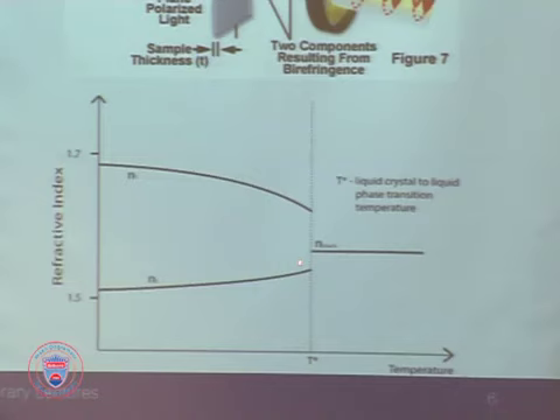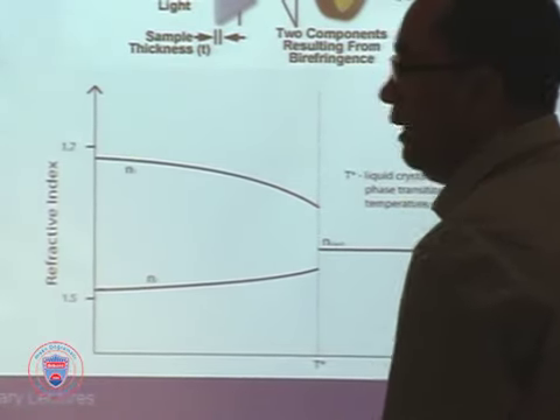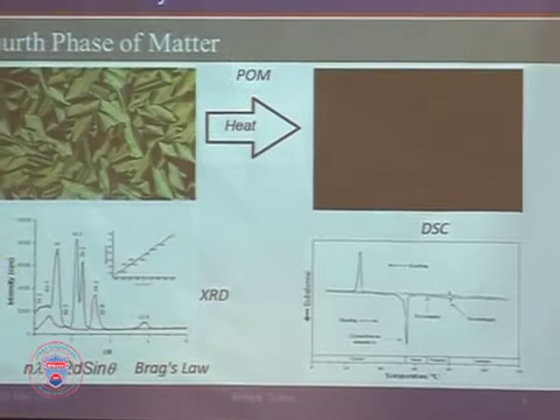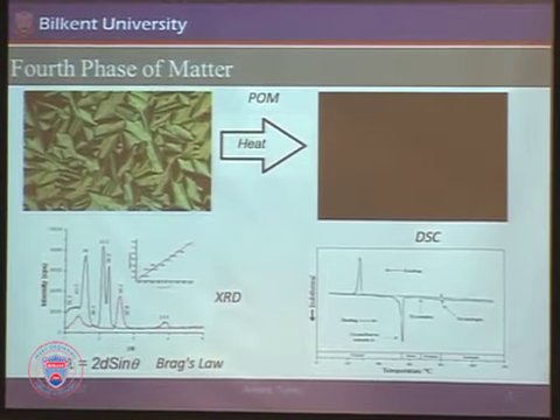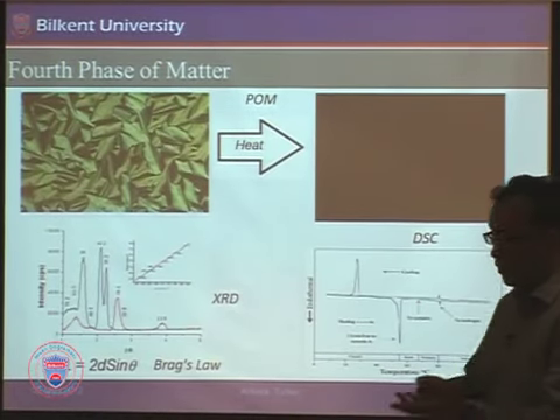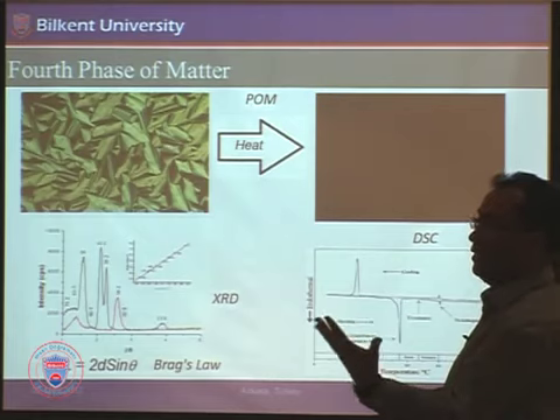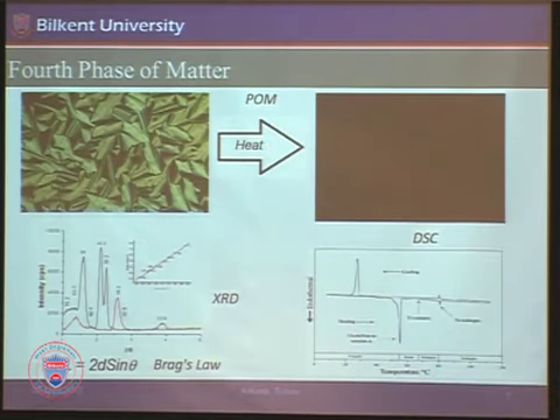And this is the refractive index, basically, of these types of materials. If you have two different refractive indices, when you heat the sample, this is the temperature axis, at some point when your liquid crystal melts, it becomes a single refractive index. Basically, this cannot distinguish the light, but this can distinguish the light. In a way, you see something at the end. Under the microscope, if you have an anisotropic liquid crystal material, you see some sort of a texture. This is related to what is really going on in there, but you see something bright in there, some color, some image. When you heat and melt, you go to a dark stage. And in a liquid crystal display, basically you are switching between those two, dark versus light.